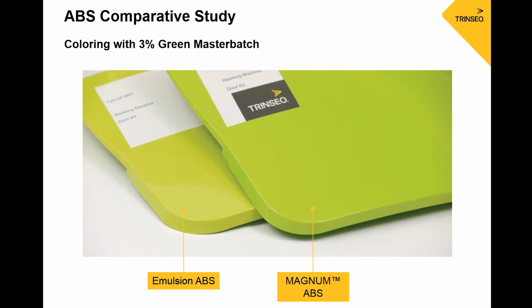So it was very exciting to see this. And not only that, even in something like a yellow, I've seen where we were able to reduce the colorant in that product. And these chromatic colorants are very expensive, much more expensive than TiO2. So even small changes can lead to very good cost savings in other colors as well. Even in that yellow color, where you see the emulsion product is more yellow, you might think that it might not be an advantage there because you're starting with something more yellow, but you're actually having to cover up that specific hue of the emulsion product. With the more pure mass ABS product, you're able to highlight the colorant itself, and you're not having to cover up that substrate material.